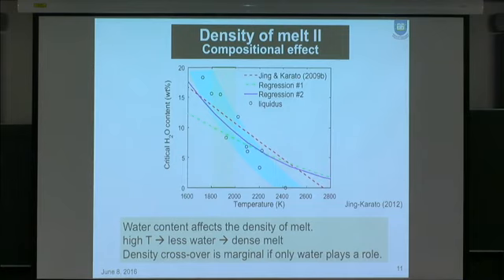When melting occurs at high temperature conditions, not much water goes to the melt. So therefore, melt is dense. But if melt is formed under relatively low temperature conditions, then lots of water goes to the melt. That's the only way to make a melt at low temperature conditions. In these conditions, melts might be lighter to make volcanoes originating from the transition zone, for instance.